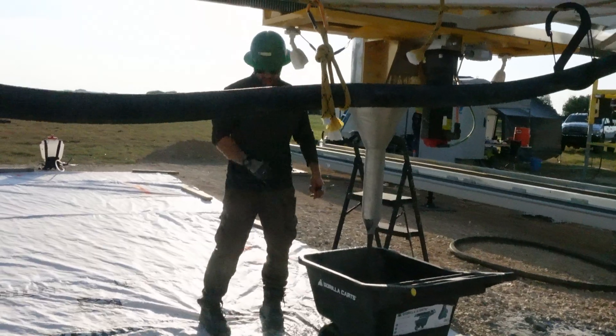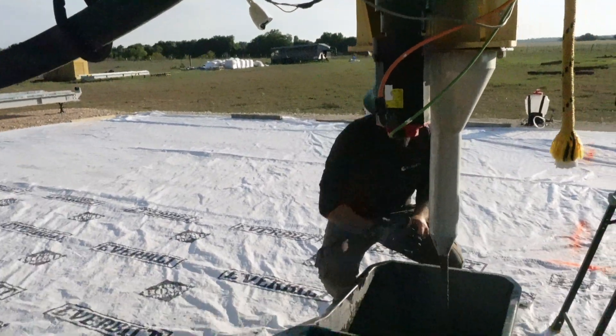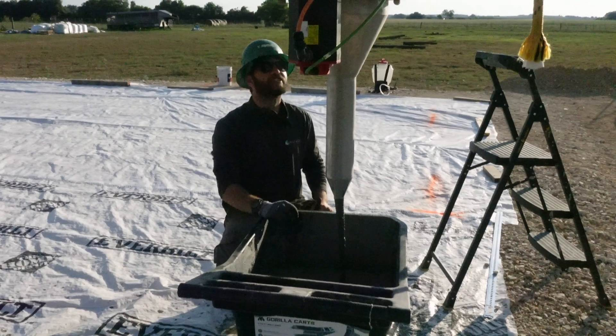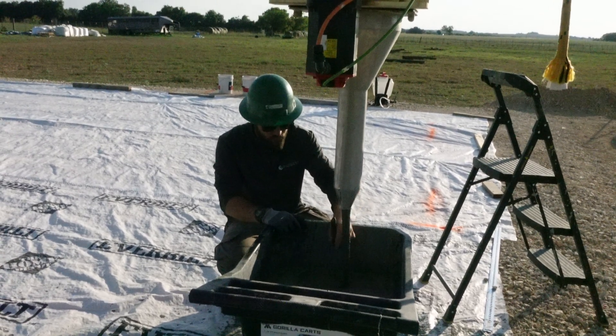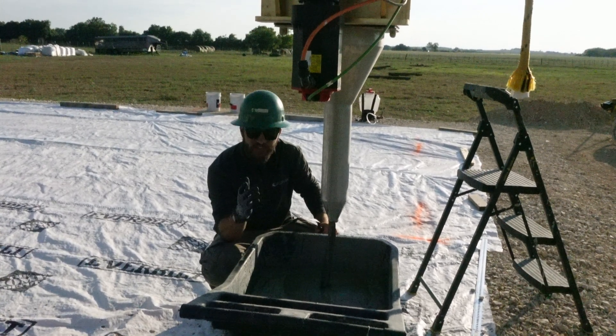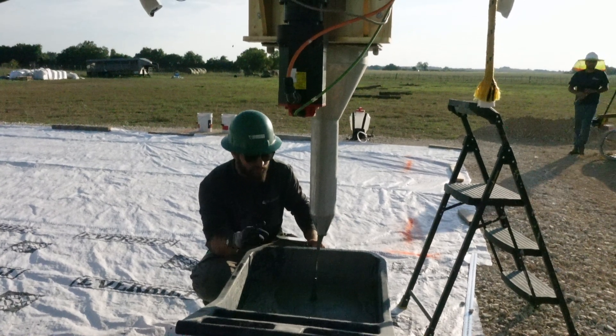It's the calm before the storm. They're preparing to get the mixer pump system going, running the wet material through. The dry layer tests are over, so in a minute they'll begin this test print. Before the initial process, you put water through and then slurry. The material is starting to come through, but equating the viscosity to food, right now we're a very soupy mixture — there's immediate slumpage, so we can't let this run. The nut is off so material is bypassing the auger system. It's way too wet — you have to go from soup, like a saucer of ice cream, and then finish on a really light play-doh material.